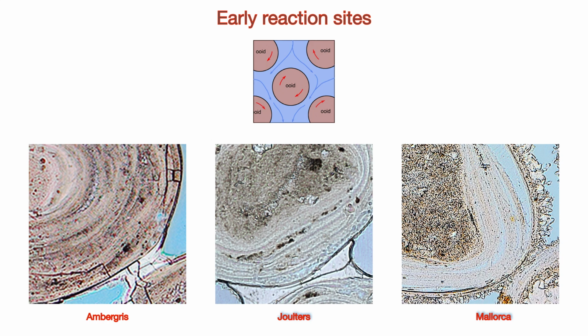Also, the Mediterranean crystals precipitated as a fringe on all ooid surfaces and kept their final growth surfaces, while the Caribbean crystals precipitated in clusters and their final growth surfaces were modified by dissolution. To speculate, these differences may be due to the Mediterranean climate being more amicable without the extreme fluctuations caused by hurricanes.